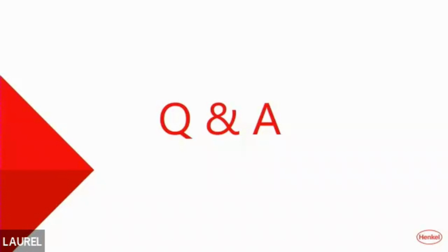I'll take one more question here. Zirconium is an ambient temperature technology, but how important is temperature and humidity control in the post cleaner stages? Great question. Increased temperature in a zirconium bath will cause the reaction to happen at a quicker pace, certainly. So you typically get higher coating weights the warmer the zirconium bath is. It doesn't have a huge impact on it. The absolute largest impact on zirconium coating weight is process time. We can make some chemical adjustments, temperature adjustments and fluoride adjustments that will affect coating weight, but not nearly as much as process time. What was the last part of that about the cleaner?